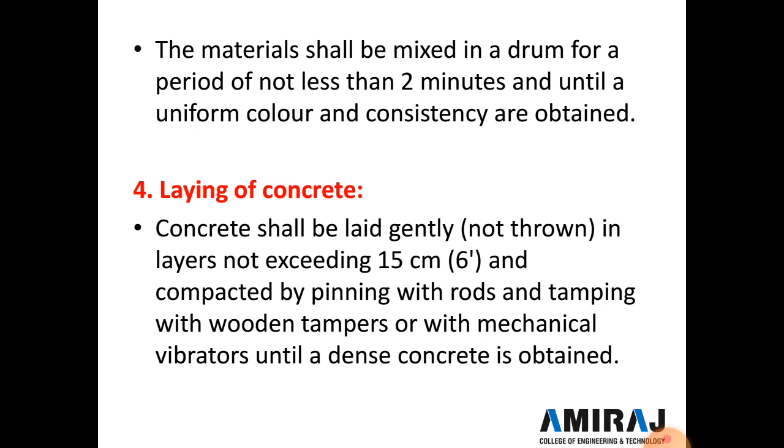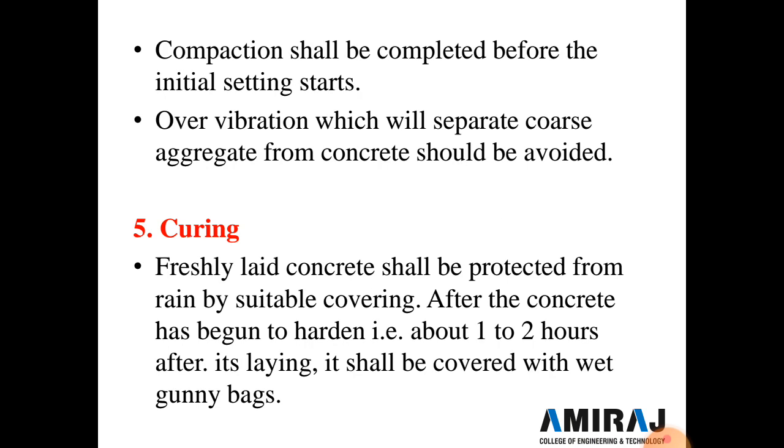Now the fourth point is the laying of the concrete. Concrete shall be laid gently, not thrown, in layers not exceeding 15 centimeters, and compacted by pinning with a rod and tamping with a wooden tamper or with a mechanical vibrator until dense concrete is obtained. Compaction shall be completed before the initial setting starts. So within 30 minutes after addition of the water we use the concrete, and over-vibration, which will separate the coarse aggregate from the concrete, should be avoided.